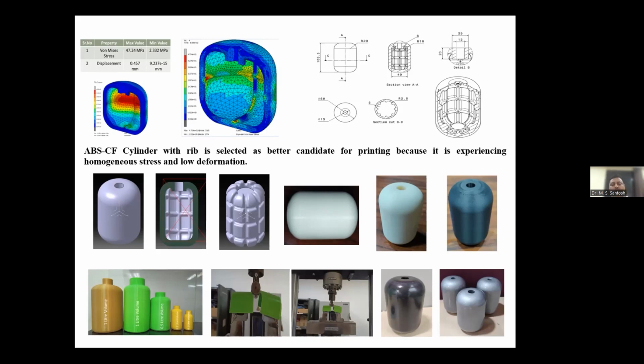The white cylinders that you see are the plain ABS materials that were initially printed in order to test the strength of these liner materials, whereas the black one on the right-hand side is the carbon fiber blended ABS, which showed a significant color difference as well as a drastic increase in the material's strength. There were other materials that we also printed as showcasing prototypes or dummy models, where different volumes were prepared and mechanically subjected to tensile property analysis as well.